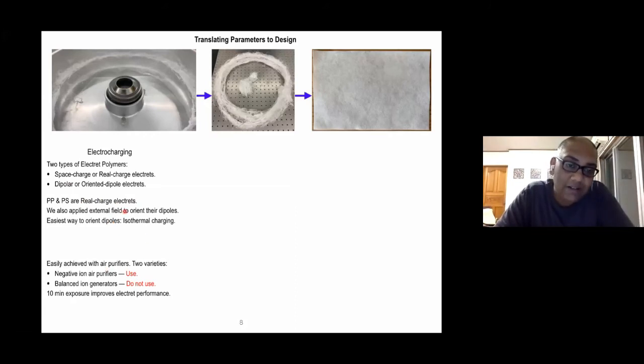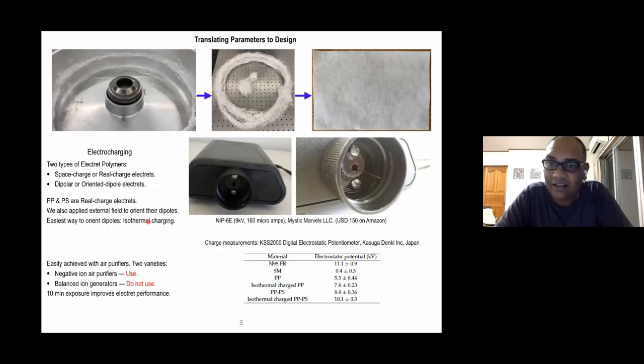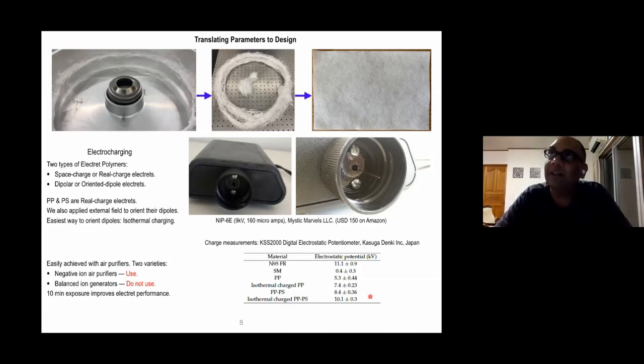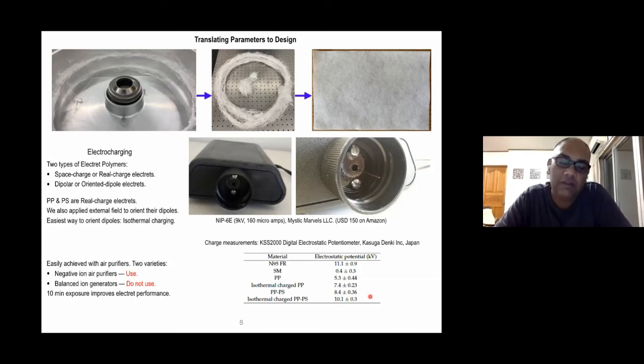But the charge that was induced through this isothermal charging method was decaying within about a week, and I realized that was due to humidity. I have not done systematic tests yet by controlling the humidity, but what I could measure with the potentiometer was that the charge we induced through these air purifiers was dying out. For example, if my polypropylene layer gave me about 5.3 kilovolts, that remained throughout these 2 or 3 months. But if I induced this charge isothermally and took it up to 7.4, within about a week to 9 days, it would come back to roughly 5.3 kilovolts. So that much is being decayed.